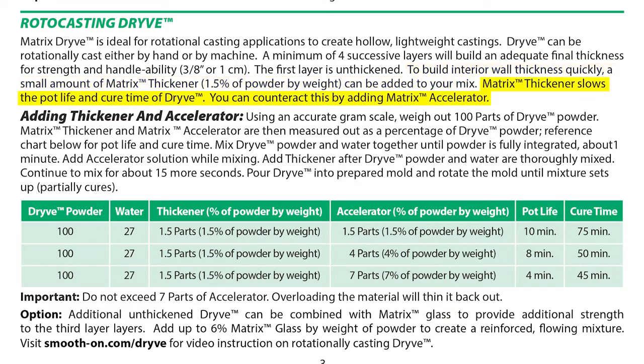It's really important to understand that the addition of the matrix thickener will slow the pot life and cure time of the Matrix Dryve. So when adding thickener, your working time and your cure time will be prolonged. We're going to add some extra accelerator to the batch that we're mixing the thickener in. And if we follow the instructions in the technical bulletin here, it shows that by adding 1.5% of the thickener to the mix, we're going to need to add 7 parts of accelerator to obtain a 4-minute working time from the material. You'll also notice there's a note that if you exceed 7 parts of accelerator, you will overload the material and it will thin out again. So it will render the thickener useless.